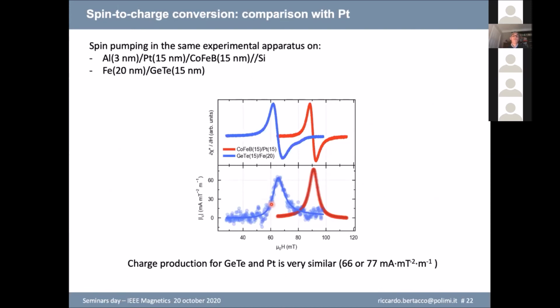The question is, what is germanium telluride in comparison with platinum? And these are experiments carried out in the same experimental apparatus on two different slices. One was platinum and cobalt iron boron, the other one was iron and germanium telluride. And you see the two ferromagnetic resonances, in blue germanium telluride, in red the case of platinum, and also the charge production curves here. As you can see, the order of magnitude of the effect is the same. It's 66 milliamps, millitesla to the minus 2 meter to the minus 1 for germanium telluride and 77 for platinum, which means that the entity is very, very similar.